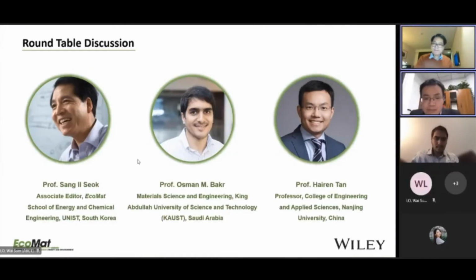Yes, I think in principle it's possible to tune the band gap by mixing lead and tin to get band gap values between 1.2 eV and 2.3 eV. I think that is possible. But one challenge we found in this community is that, for example, if we want to make the ideal 1.35 eV band gap, the tin ratio is around 25% to 30%. And it's very interesting that in this mixed system, if the tin ratio is only 25% or 30%, usually the electronic quality of the perovskite film is very poor. And the reason is still not quite clear.